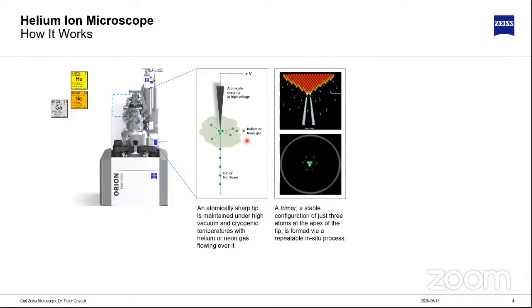Okay, if we look a little bit closer to that tip, so that's actually the special thing about this type of microscope. The tip consists of a single crystal tungsten tip. And if you have the right orientation, then you can sharpen this tip in a way that you end up with only 3 single atoms at the very apex. And that means if we apply this voltage here to the tip, then we have the highest field in front of only these 3 atoms. That means only in front of the 3 single atoms, we have ionization conditions for helium atoms. That means we only generate ions in front of these 3 single atoms. And that means we have an extremely sharp tip that only consists of 3 atoms.